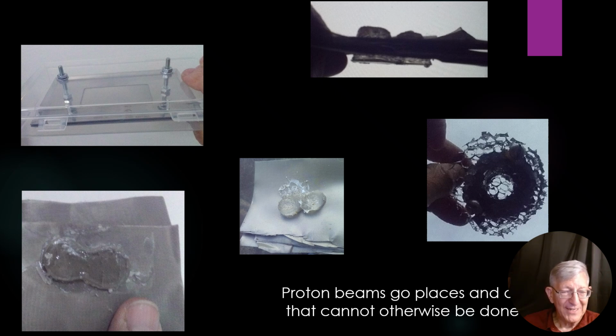The solid resin was penetrating through the aluminum screens, essentially like a couple of nails that went through there. And I think this implies that there is a manufacturing application, considering especially that we worked through several inches of water, went through the plastic, went through the resin, and produced these penetrating solid resins in the right places. Now, at the top, what you see is a profile of this whole thing. So you see the depth of the proton beam induced solidification of the resin, and so these four photographs together give you a very interesting insight into the type of thing we could do with this.